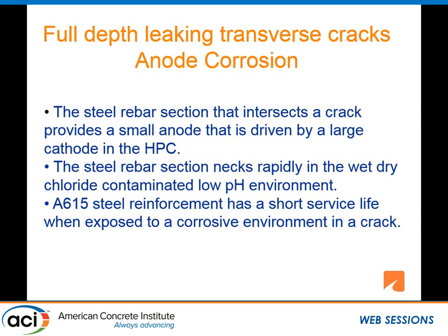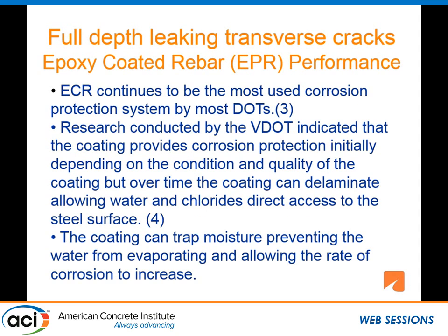What we have here in these cracks is anode corrosion. The rebar section that intersects the crack provides a small anode that's driven by a very large cathode in the rest of the deck, where the high-performance concrete has high quality. So the steel section necks down rapidly in the wet-dry, chloride-contaminated, low pH environment. In this situation, A615 steel rebar would have a very short service life. Now, how does epoxy perform in a situation like this?